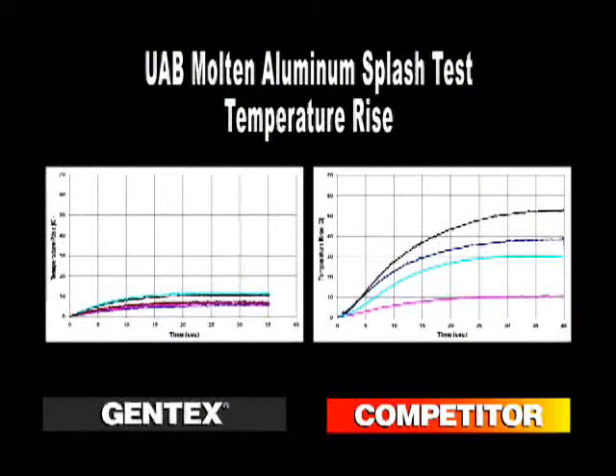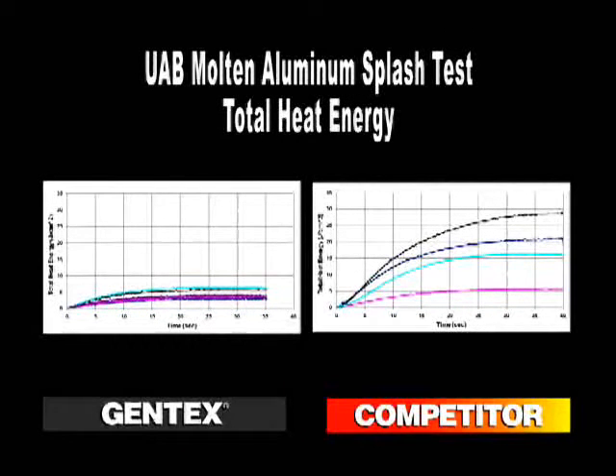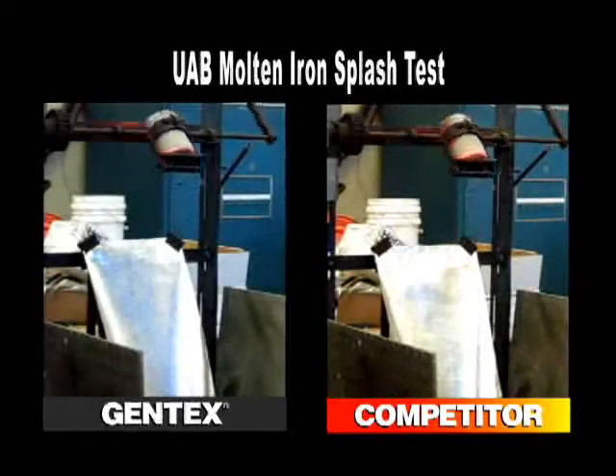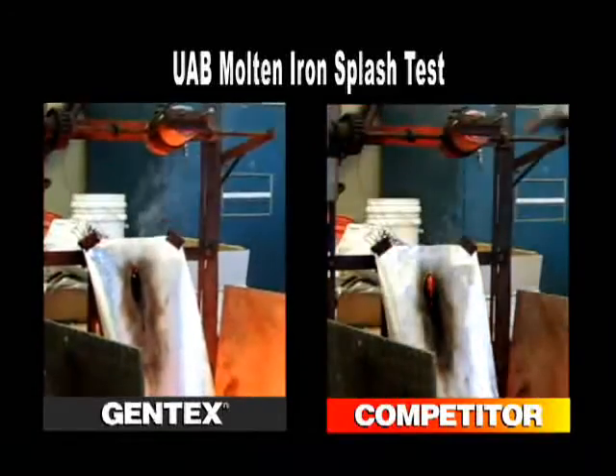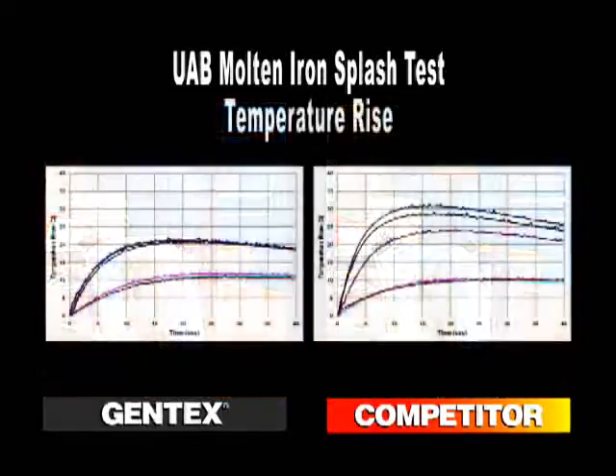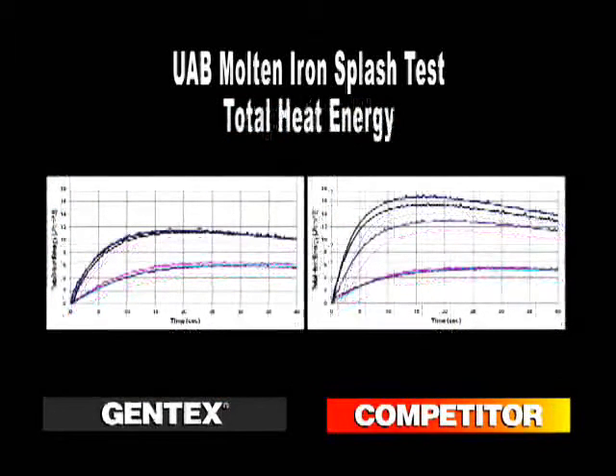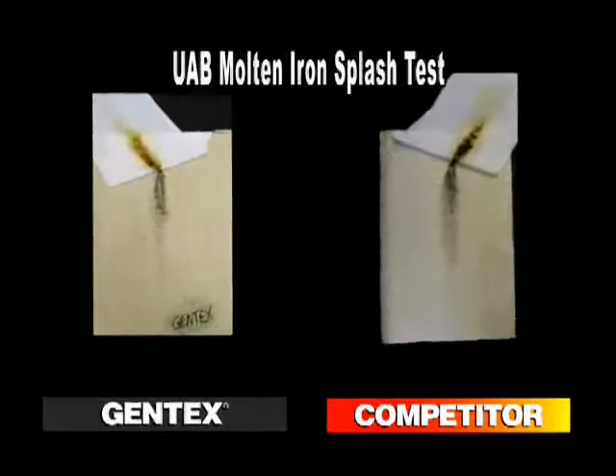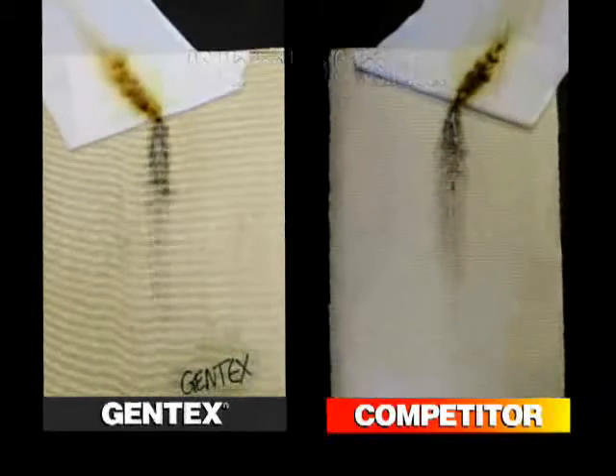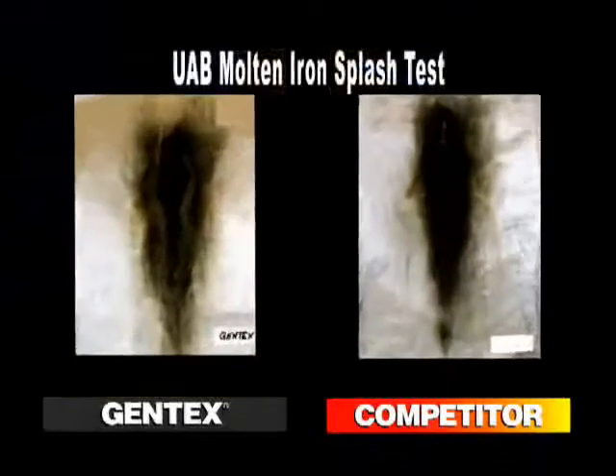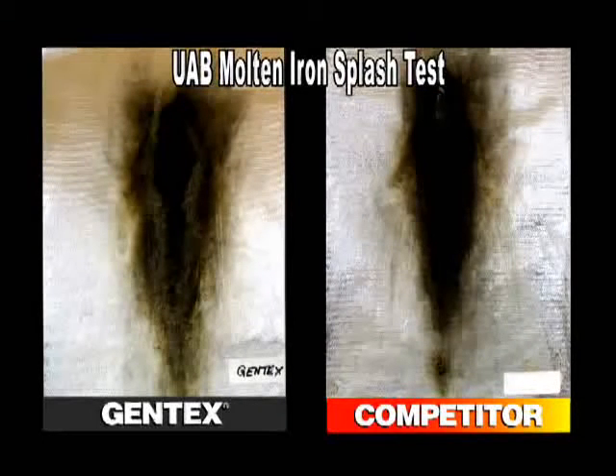Take notice of the temperature rise and the total heat energy data charts shown here. Upon comparison of the highest heat transfer values on these charts, you will notice that there is at least a 300% delta in both temperature rise and total heat energy between the two aluminized fabrics, favoring the Gentex fabric. In this side-by-side comparison of molten iron testing, you will notice that the molten iron is shed successfully by both the Gentex fabric and the competitor's. The true difference between the two can be found in the temperature rise and the total heat energy results seen on these charts. As you can see on the back side of the splash fabrics and on the data charts, the Gentex fabric on the left allows 30% less heat to transfer through the fabric upon impact of the molten iron than the competitor's fabric on the right.